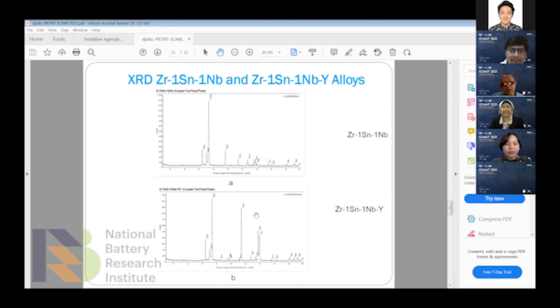This is the XRD examination from this figure. This alloy consisted of alpha zirconium. This is the main peak of the alloy, and these minor peaks are beta zirconium. It is the same; the two alloys are not really different. The X-ray diffraction peaks are relatively the same, but the peak is relatively bigger in the alloy with the addition of yttrium.